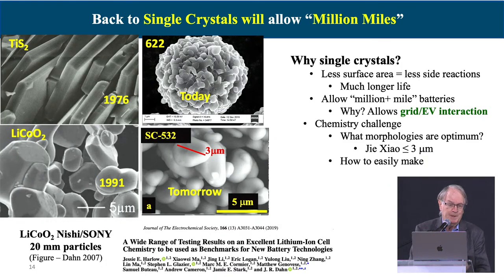So I show you four pictures here. The original TiS2, you can see how big those single crystals were. Beneath that is lithium cobalt oxide. This is from Sony. Sony tried to make the lithium cobalt oxide as big as they could because they wanted to make those batteries safe. But as we moved on from the 1990s to the 2000s and 2010s, people wanted more and more power. So we went to these meatball morphologies, much more surface area, therefore more rapid reaction rate, discharge rate, but also reactivity with the environment.